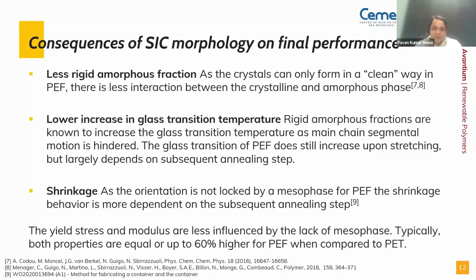Now if we look at the impact of all these effects, then how can we summarize and correlate the impact with the processability and the product properties? So in case of PEF, there are fewer rigid amorphous fractions, because as I mentioned, the crystals are very clean. So there is less interaction between the crystalline and the amorphous phases, and therefore the amorphous region is less rigid, which has an impact on the glass transition temperature. The rigid amorphous fractions are known to increase the glass transition temperature, as main chain segmental motions are hindered here.